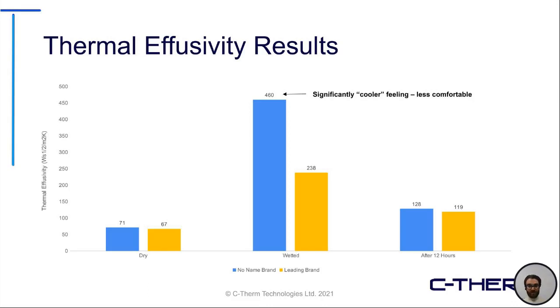Now, after a 12-hour period, we came back and tested the sample again, and we noticed that the difference became a little less significant after that extended time duration, most likely because even though the no-name brand wasn't as efficient at dispersing that liquid from the top layer into the absorbent core, given enough time to reach there, it did have a more comparable result down the road. Again, fairly similar, but still a little cooler feeling at the end of the day.